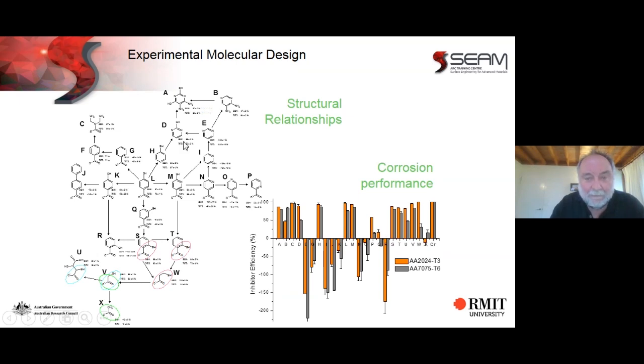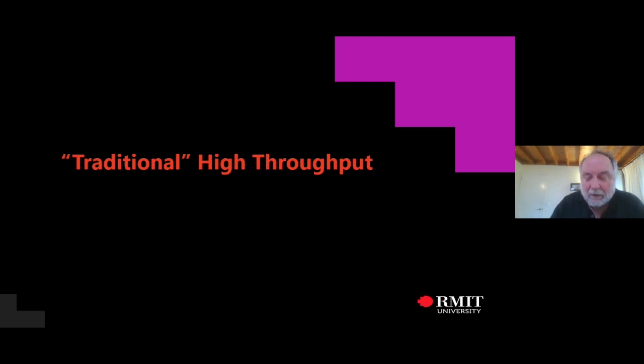And we can see that if we go from inhibitor D with the linker group to inhibitor E without the linker group, we dramatically shift the performance and go from quite a good inhibitor to a corrosion promoter. And similarly, other small changes in the molecular structure dramatically change how the inhibitor performs. So we need to get not only the right type of inhibitor, but the right isomer amongst the different families. So we've traditionally done that by high throughput experiment.